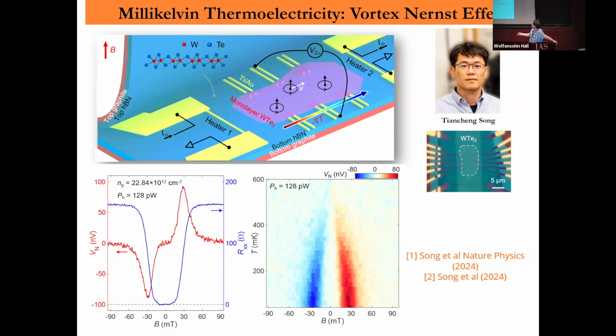Now if I turn off the current and only look at the voltage developed by applying a temperature gradient, there's no electrical charge current, only a temperature gradient. Now you see the red curve—the Nernst signal, which reverses its sign when you change the B field. There's no signal here at very small field because there's either no vortex or the vortex is not moving, so you have a very good zero resistance superconducting state.